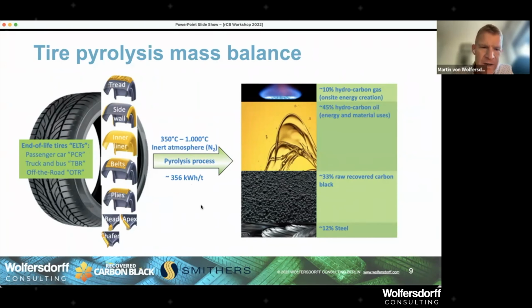And now the new part is about the energy use. And I think this is, if you ask me what is the next level of benchmarking technologies in tire pyrolysis and recovered carbon black production, it's how much energy you need for the pyrolysis process. Clearly, we'll talk about the post-reactor process, the milling, pelletizing a little bit later on, and they are also energy hungry, but the most energy consuming part of the process is the pyrolysis, because we have to break up these sulfur vulcanization bonds of the rubber chains.